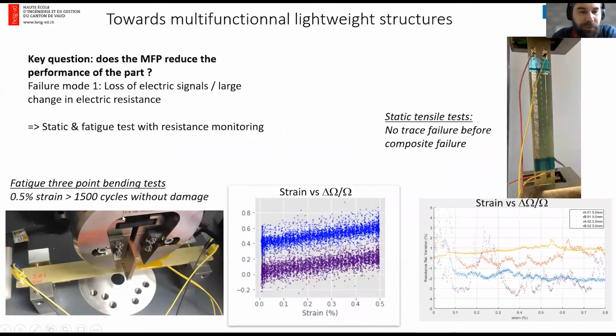So the main question when we integrate this in a structure is, do we lose strength of the laminate by integrating an active layer like this? So we looked at the different failure modes. One of the critical failure modes is the loss of electric signals, because if it's a critical signal, we cannot lose it, or we lose the aircraft or the UAV. So we did fatigue testing of printed layers in 3-point bending and also static testing in tension. We observed overall that the traces are actually stronger than the laminate that we were using. So we didn't see any degradation before the composite failure. And we have a limited sensing ability, so these kind of traces are not really good for sensing. They are optimized for signal transmission and power supply.